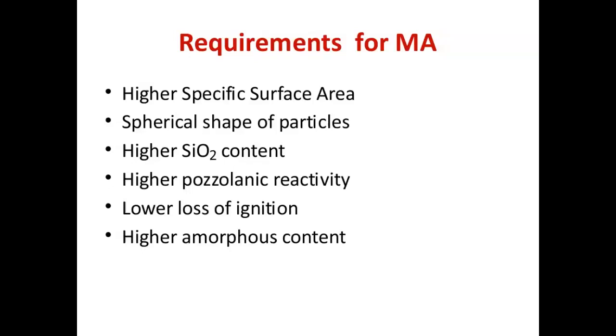Higher specific surface area. Normally for cement, the specific surface area is 300 to 400 square meters per kg. That means when you spread 1 kg of cement, it will occupy a surface area of 300 to 400 square meters. Whereas mineral admixtures like silica fume and metakaolin have a specific surface area of about 20,000 square meters per kg. That means 1 kg of these admixtures will occupy around 20,000 square meters. Its fineness is more, so very quickly it will react, and we will get early strength in the concrete.